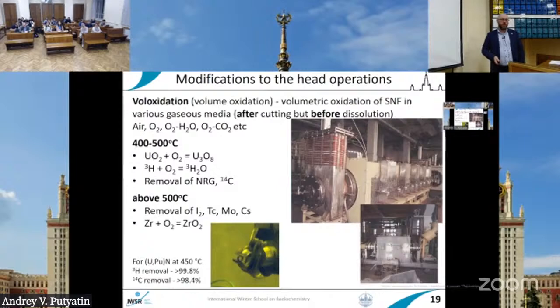The modification of the first head operations is the oxidation of the spent nuclear fuel in gaseous media that is called voloxidation, volume oxidation of the components of the spent nuclear fuel. And the voloxidation can be performed after the cutting or chopping of the spent fuel assemblies, but before dissolution. The main idea of the voloxidation is to remove a significant part of the volatile components and especially of tritium because again, tritium is located in spent nuclear fuel, and when you dissolve spent nuclear fuel in nitric acid, the whole volume of the nitric acid will contain tritium.